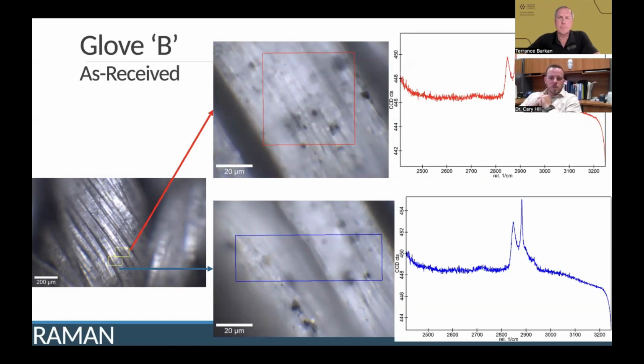So glove B was one of the gloves that we observed that claimed to have graphene content. And you can see in those optical microscopy images, these little black flecks seem promising at first. The Raman spectroscopy, this is on the surface. Raman, depending on the material, the laser is able to penetrate to a certain degree, but it's not always definitive that it's going to penetrate well enough to get a signal from any graphenic content that may be within those fibers. So on the surface, essentially, we're just seeing the polymer content here. We're not seeing anything graphenic in this range, but we don't expect to either necessarily.